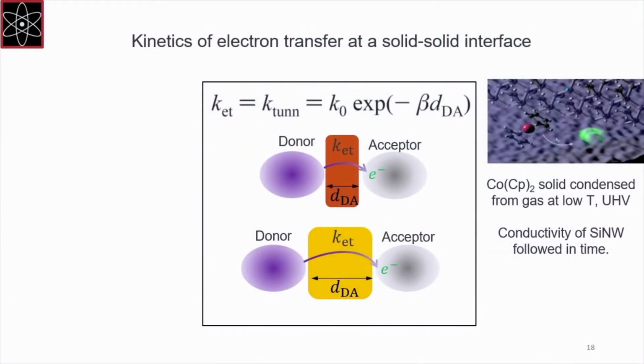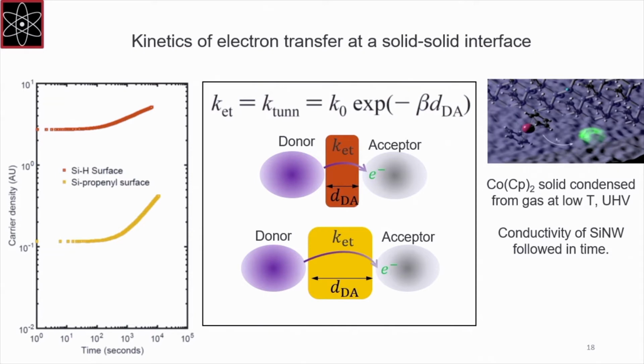To make sure that things make sense, the parameter that should lead to the most sensitive response in the system is the separation in distance between your donor and the acceptor. Donor in this case is the molecule that's yielding the electron to the silicon sensor, which is also the acceptor. And the way we achieved that experimentally was by using surface chemistry, gas phase chemistry that we developed actually for making cantilevers more sensitive. We applied the same chemistry to the silicon nanowire sensors. So one surface was just, everybody knows, hydrogen terminated surface. Another one was a silicon propenyl surface.